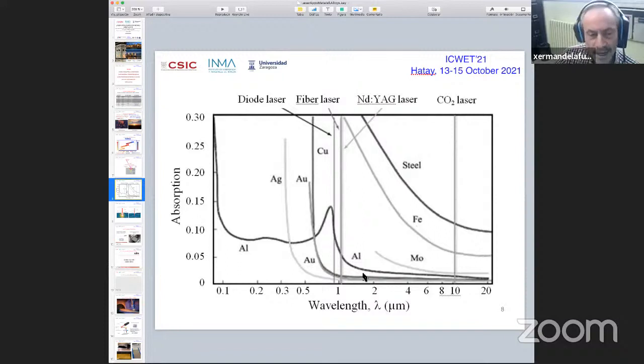but not as much as other upcoming lasers like the solid state and nowadays the diode and fiber lasers. The reason why the diode laser would be used is because for aluminum, for example, it has a much higher absorption than the fiber laser. You can see here the difference. And the fiber laser is much more absorbed by most metals than the CO2 laser. So the fiber laser has many advantages from the energetic point of view, from the quality of the output point of view, and from the absorption point of view to work with metals. And so it's one of the most common lasers used for metal work.